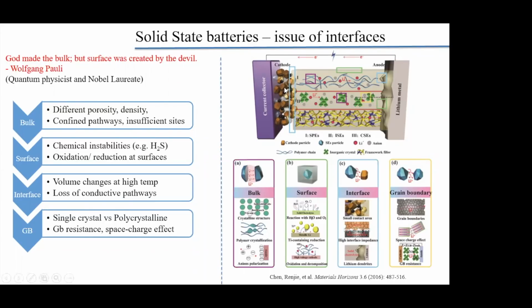And then at the surface level, you have chemical instabilities. These interfaces need to match up chemically also. If they don't match up chemically, if one of them has a tendency to undergo oxidation or reduction at the surface, that's not good. For example, sulfide-based solid electrolytes have a tendency to release H2S gas, which is not good. And that is at the surface.